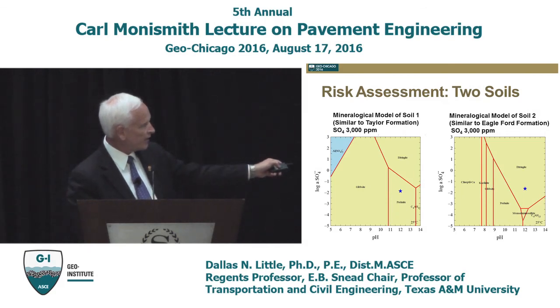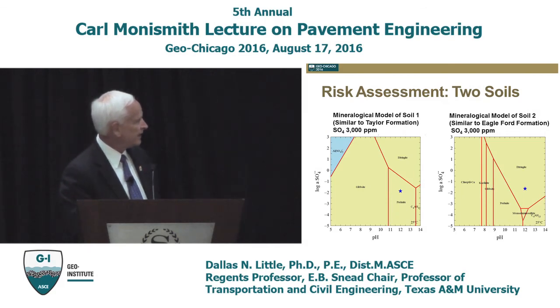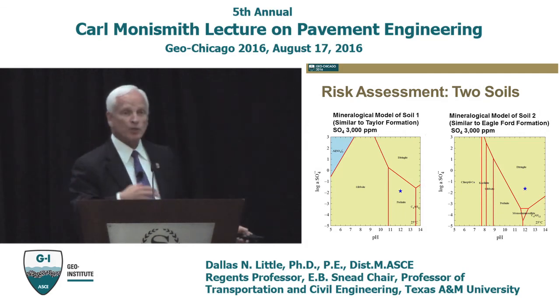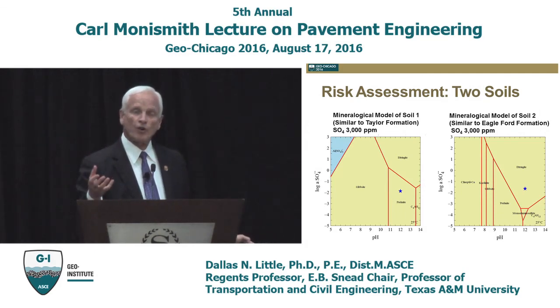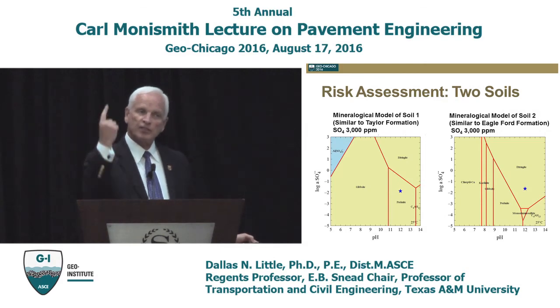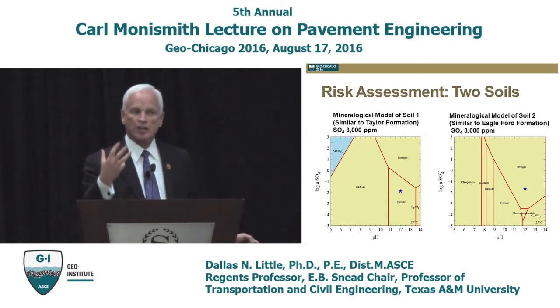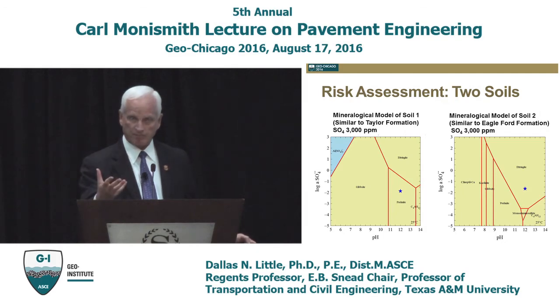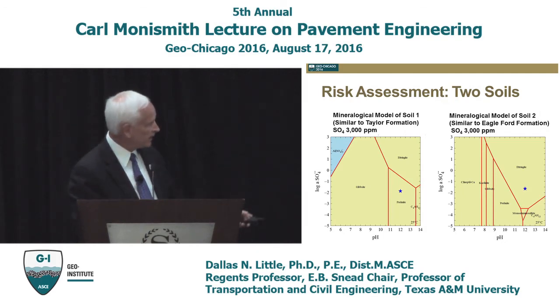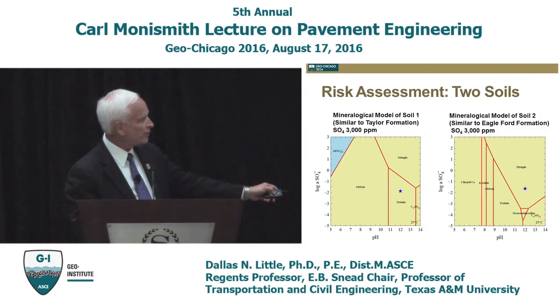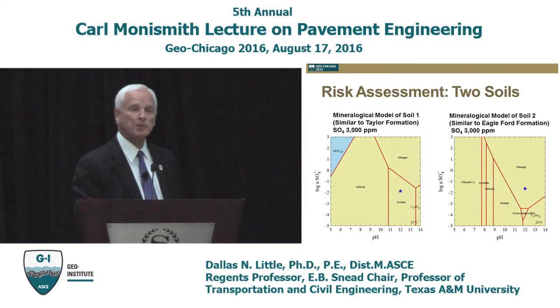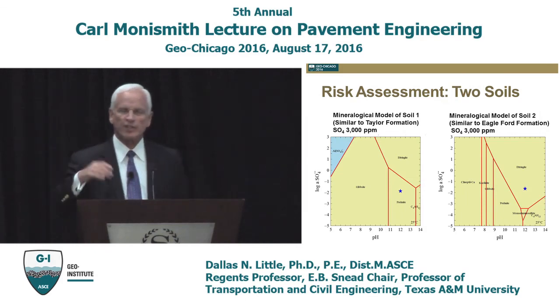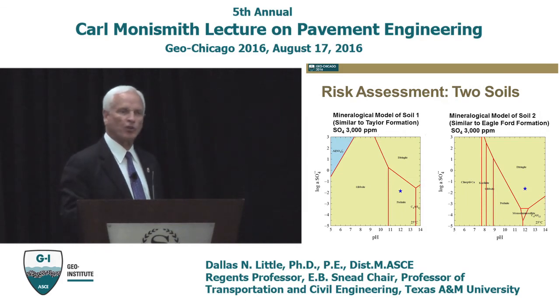This polygon over here to the right is ettringite. So, when you add lime or cement to a soil, you're going to add it to get the pH up to above 12 so it will solubilize the minerals and react with them, the silica and the alumina. So the pH 12 is what I'm identifying here by that star. The locus of that star is a pH of a little above 12 and also a sulfate content of 3,000 parts per million, which we've identified as an upper threshold.